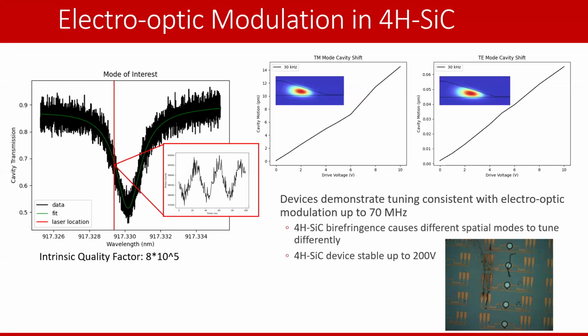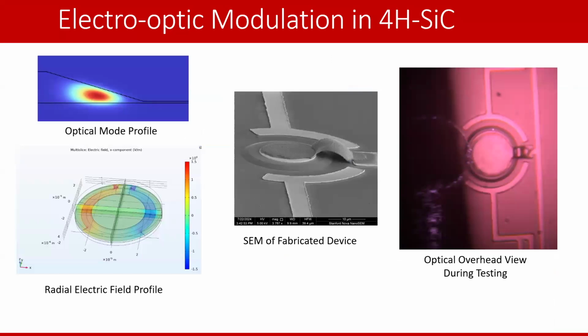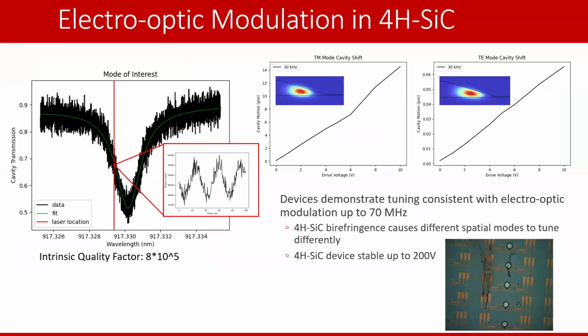And indeed, we put up to 200 volts across this gap right here. This is an 8 micron gap. And that actually was not the problem. What you see here is the blown up electrical tines from the waveguide probe that we use to couple to these devices, which implies that, as expected, silicon carbide has a very high breakdown voltage. And so you can really apply a lot of field across this direction, which is excellent for our goal of tuning defects within cavities. So this is great. The electrode design works. We can couple it to these optical cavities. Time to make devices on quantum grade material.